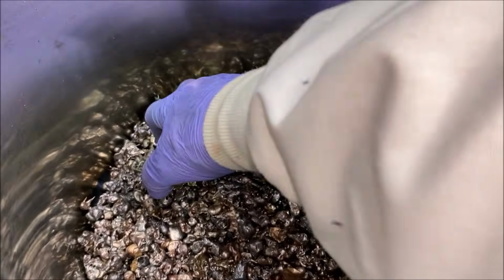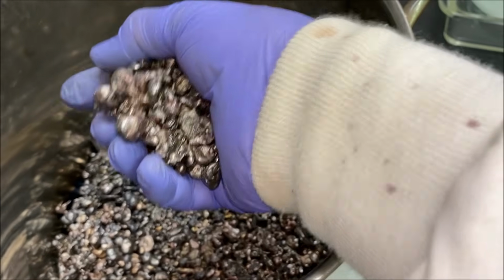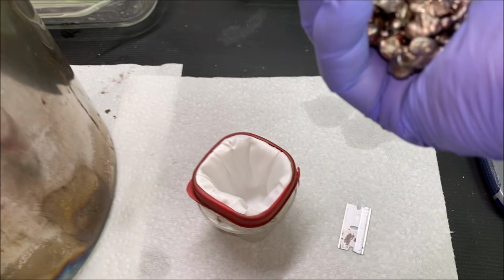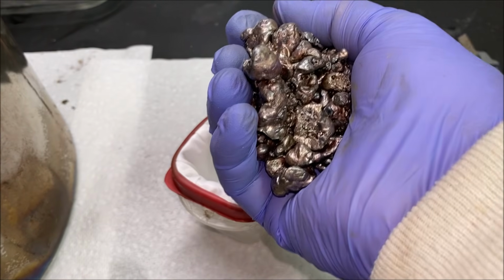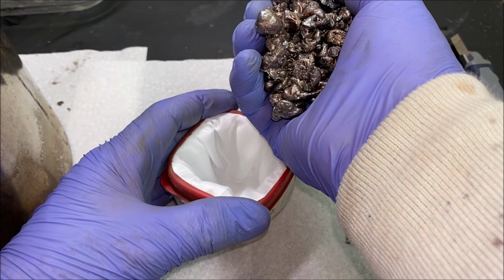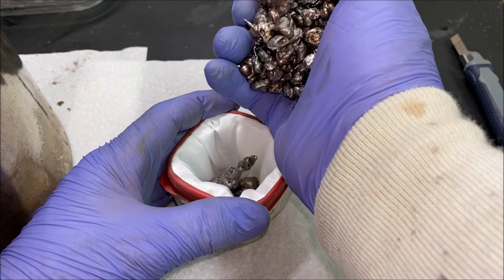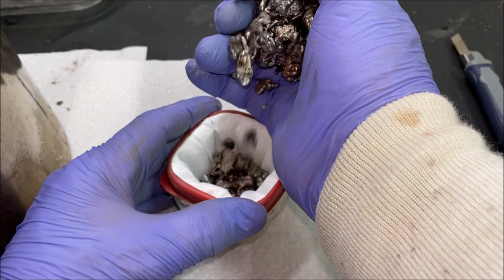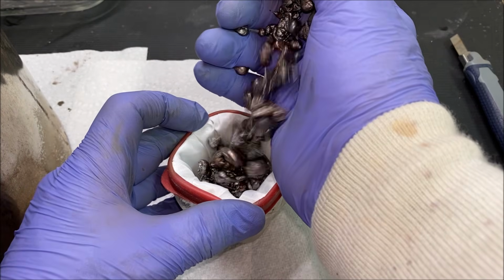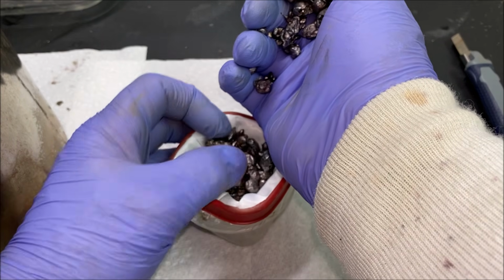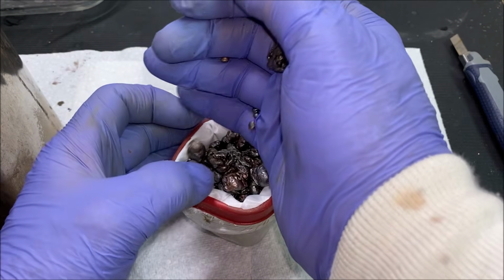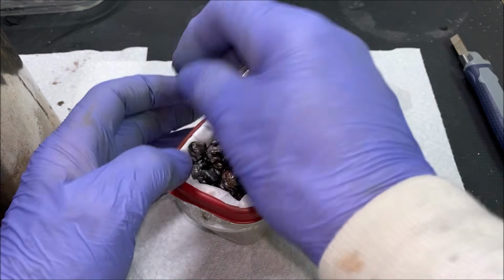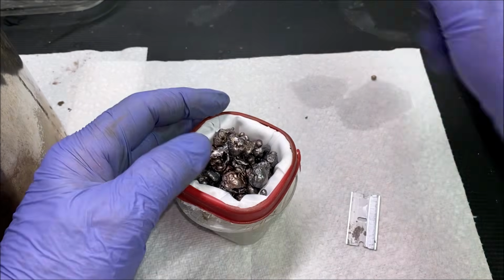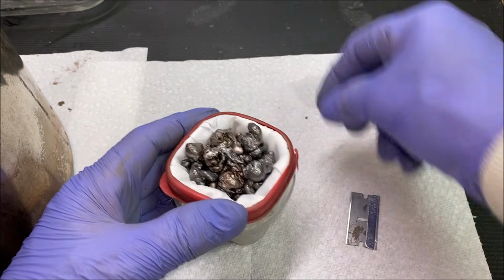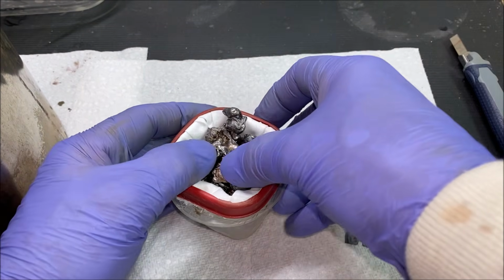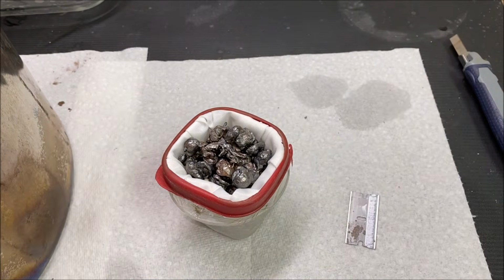Now what we'll do is come down here, get some of our silver shot. This is impure silver that we made by melting cement silver in our furnace and pouring it into water to form these granules. And this will be the feedstock that we use to feed impure silver into the silver cell.